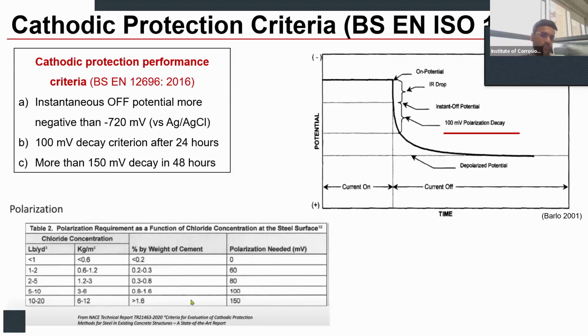If we come to the protection criteria, one part is about the anodes we use, second part is the protection criteria. As per BS 12696, 2016, and now we have a new code also in 2022, it specifies three protection criteria, so that once the system is energized, we stop the current passing and then we monitor the decay.